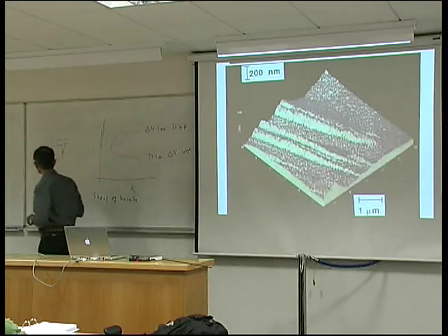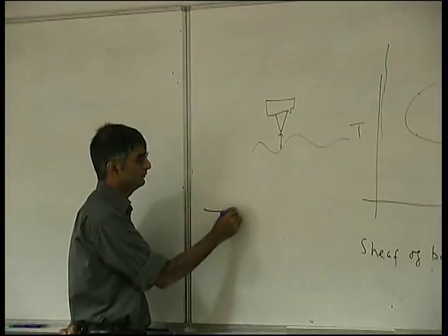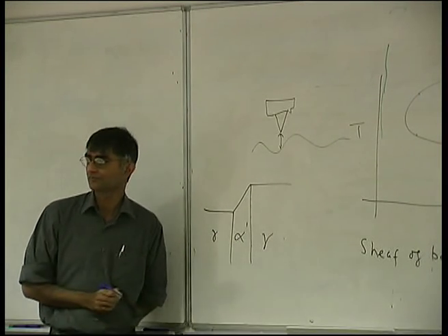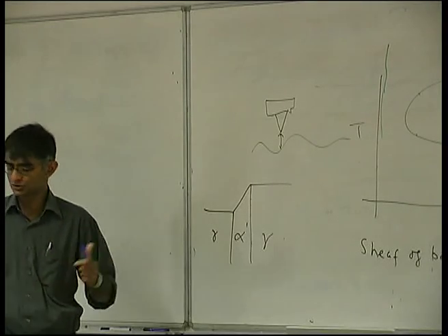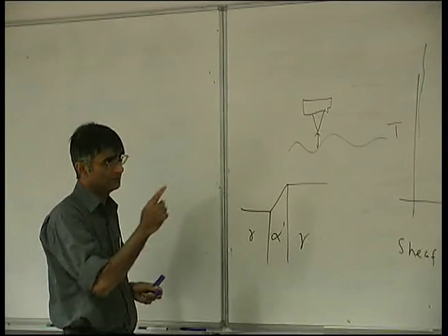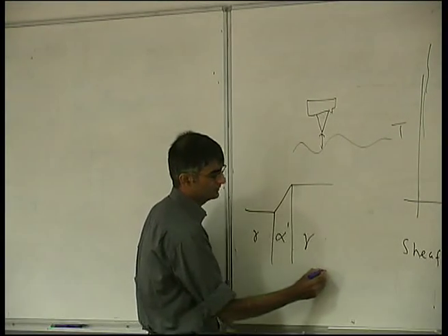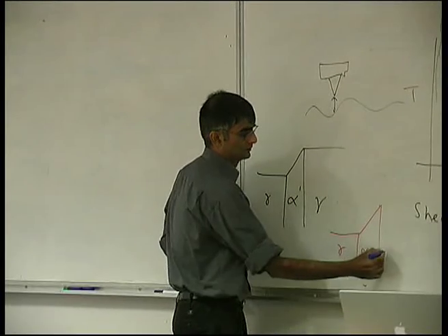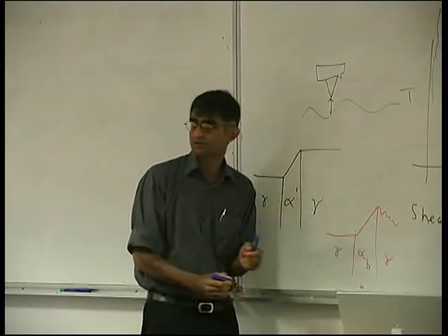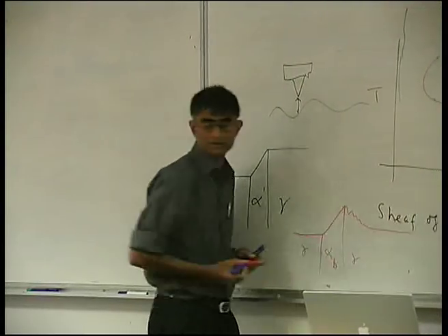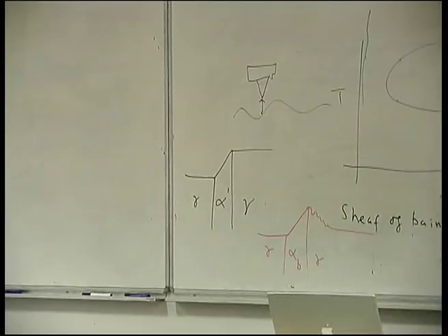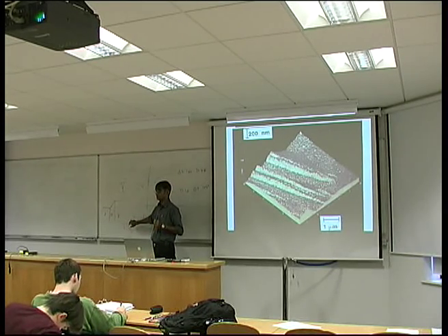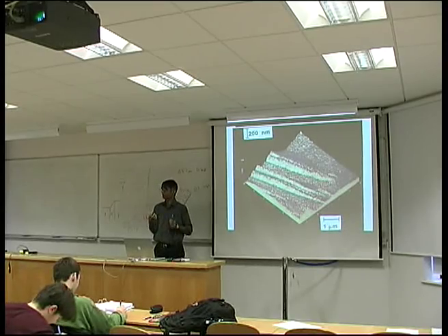Now just to illustrate that, when you form a blade of martensite, we pick up a deformation which looks like this. An invariant plane strain which has a large shear component. When we observe the shape change due to bainite, it's slightly different. Yes, we have the shear deformation, but the austenite adjacent to the bainite has relaxed by plastic deformation. You can see this curvature here. And that happens because these strains are simply too large at the high temperatures where bainite forms for the austenite to accommodate them elastically.